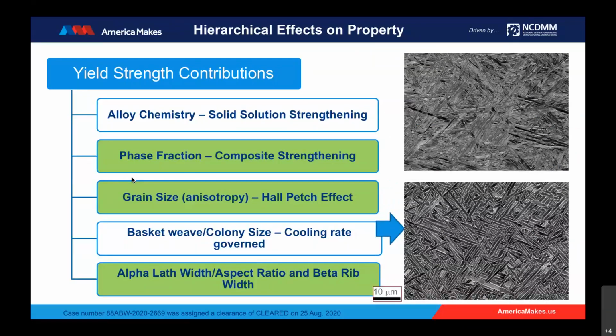But even when you have basket weave microstructure, like you see on your right side, you have the very fine scale feature size, which is more monolithic in structure, versus a relatively near-to-equilibrium microstructure, which is more alpha beta structure. Similarly, having a basket weave structure, but the yield strength contributions would be very different between one versus the other.